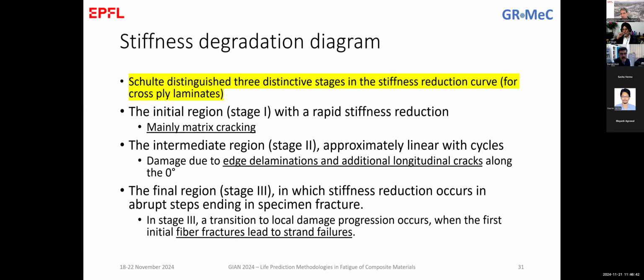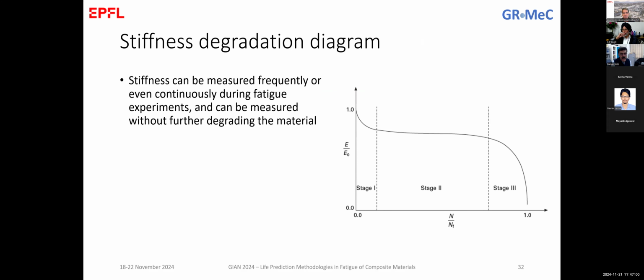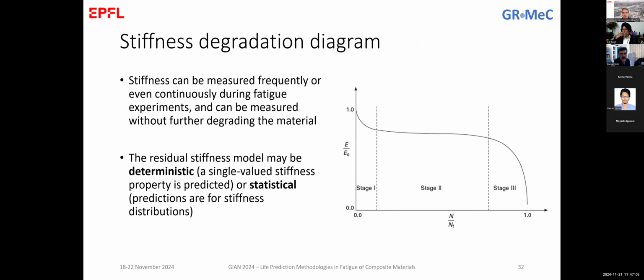Then we have the intermediate region, where we have an approximately linear degradation of stiffness with the loading cycles. And then we have the final stage 3 in the diagram, that is attributed to the final failure of the material. The benefit of stiffness, and this is why it is appreciated by engineers, is that you can measure it during loading. It's also a measure that can give an assessment of the material performance without having to do any destructive testing. So it's a non-destructive method to follow the progress of the material capacity, and as such, it can also be used as a performance criterion for the material.